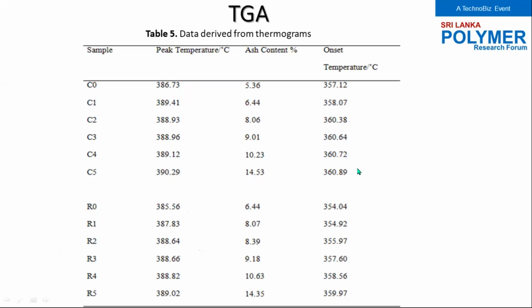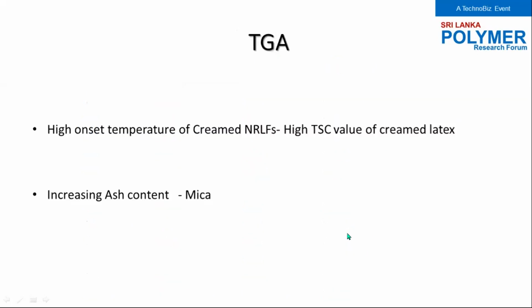From the data derived from thermograms, we can observe the peak temperature and onset temperature. There is a slower increase with the addition of mica. That means mica thermally stabilized the natural rubber latex foams, and the same pattern could be seen in the cream latex. However, cream latex shows higher thermal stability than centrifuge latex.